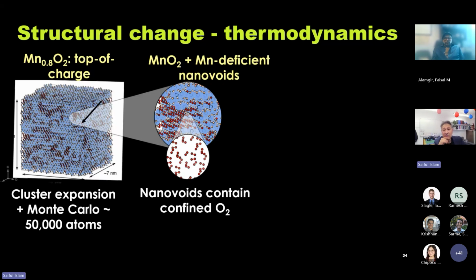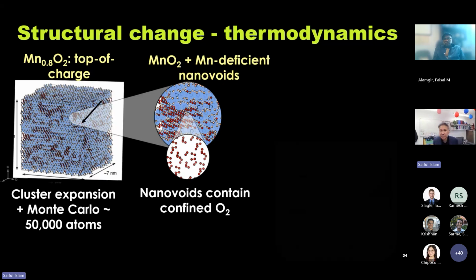What we see is phase segregation into manganese-rich MnO2 and manganese-deficient nanovoids. And in those deficient nanovoids, we've got these molecular O2 in the bulk. But they're large, and they actually can be connected to the surface for surface release. So what's the experimental evidence for this?